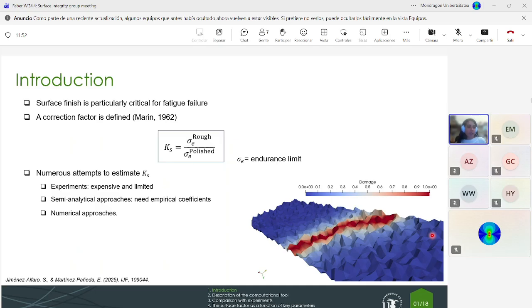We also have semi-analytical approaches in the literature. These approaches are normally related to a notch because the surface roughness topology is very similar to notches. They are very good in static because in the fracture mechanics community we know a lot about notches in static, but when we go to fatigue, then we need to include some empirical coefficients. So in the end, we need experimental data in order to fit these coefficients. So we end up with the same drawbacks as we have in experiments.